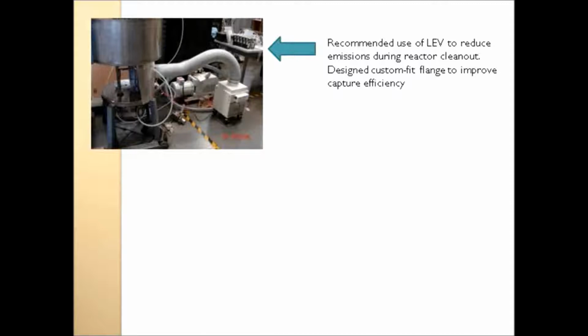Paul put the data up earlier and showed it was a dramatic reduction, 80 to 95%, on either a mass or particle number concentration basis. Just by using that small little operation, and it's mobile, it's on wheels, you can go from reactor to reactor, which is the beauty of it. So you don't have to necessarily design a very costly exhaust ventilation system. If you take something like this that's available, modify it to suit your needs, we tested it, we evaluated it, and we were very pleased with the results.